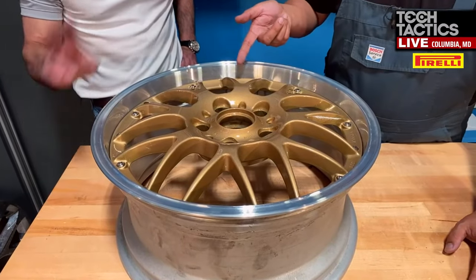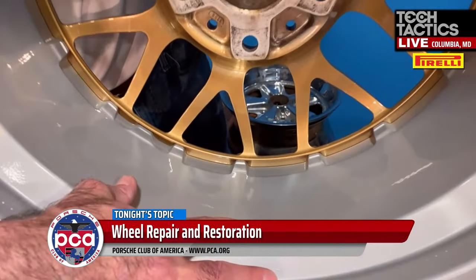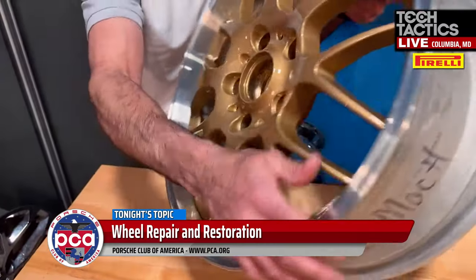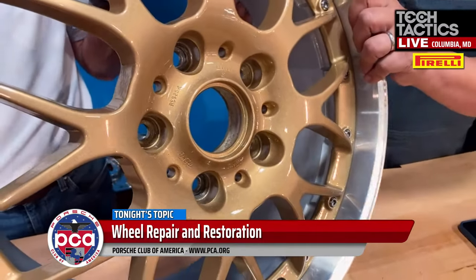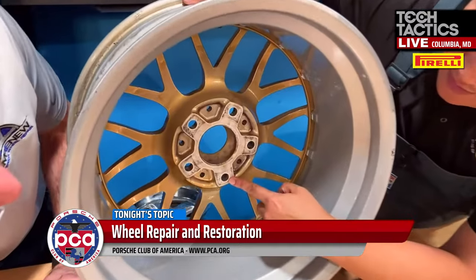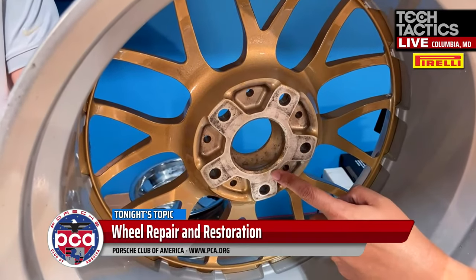Here's something important — you see all this beautiful powder coat, nicely finished. However, you see this mating surface here looks unfinished. There is no powder coat there. I know of other wheel companies that also painted that area — and that was a big no-no. You want to share why that's a no-no? With powder coat especially, because it has a bit of thickness — it's essentially plastic, polyester and urethanes — if you get it on this mating surface and don't remove it, you have an extra layer between the hub and the wheel.